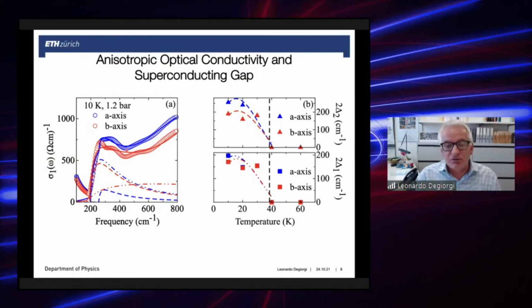There are theoretical ideas proposing indeed a so-called orbital differentiation upon applying an external symmetry breaking field, which might lead to an anisotropy in the effective mass of the itinerant charge carriers, which is then basically related and pairs with what I said before concerning the anisotropy of the suppressed spectral weight itself. And by the way, this orbital differentiation or differentiation of the effective mass seems to be further enhanced by correlation effects, which for hole-doped materials are actually very important.